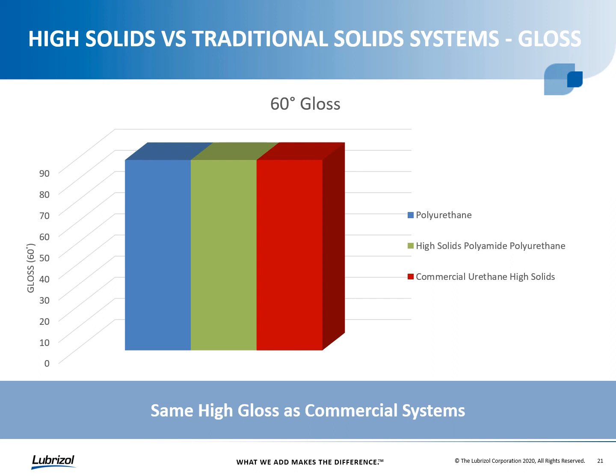When we compare the 60-degree gloss values of the high solids polyamide PUD versus traditional solid systems, we see that the high solids resin is capable of delivering very high gloss values, much in line with the traditional PUD as well as the high solids commercial benchmark product. And here we see the 60-degree gloss for all 3 products coming in at just over 90 units at 60 degrees. So delivering very high gloss but also having the ability to be matted down with some surface modifier to get the gloss down if you wanted more of a satin or a low gloss finish as well.